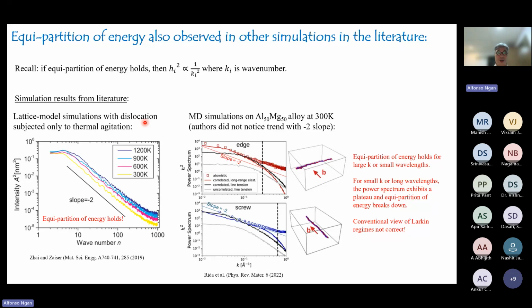Then we looked at the literature, and we actually discovered that other people have also observed the Boltzmann distribution. In fact, they observed the equipartition of energy. So again, to recall, if the equipartition of energy holds, then we expect the amplitude square of each harmonic to be inversely proportional to the wave number squared.